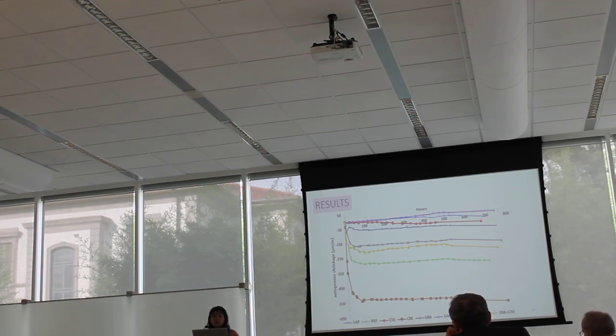Then you have the mixture with the SAP, the blue one, and it has until 28 days like 15 micrometers, which is almost nothing. So the amount of internal curing water was correct.